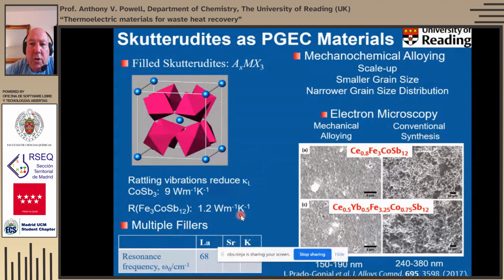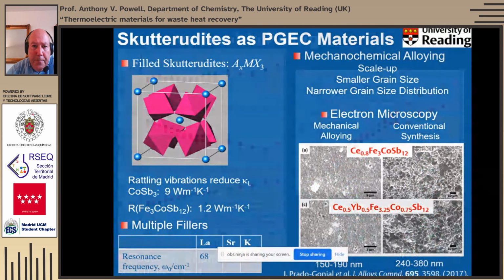So that was our motivation, and also because we were working on a project related to energy recovery in exhaust systems, we wanted to be able to scale up. So we started looking at mechanochemical alloying to make these materials. That allows us to make batches significantly larger than traditional sealed tube synthesis. As we can see from the electron microscopy here, these are mechanically alloyed materials, and here are materials synthesized conventionally by high temperature methods. It gives us both a smaller grain size and a narrower grain size distribution. So the grain size is quite significantly smaller than in the material from high temperature synthesis.